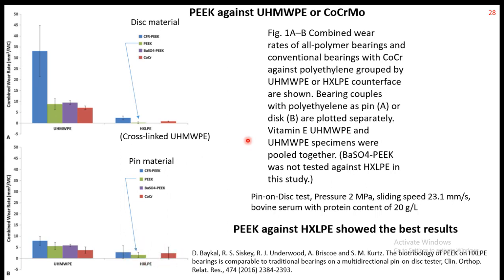So overall it is concluded here in this work that PEEK sliding against UHMWPE has better results than PEEK sliding against cobalt chrome molybdenum. However, I should say that this kind of result needs to be verified by a third party, because in this work the study itself was supported by the company which made the PEEK. So it needs to be verified by independent research.